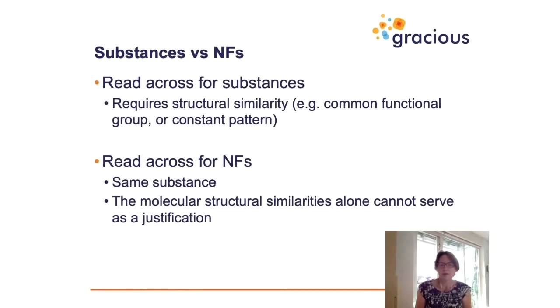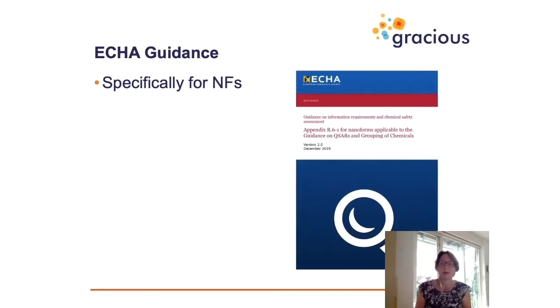So for nanoforms, read across is used in general only within the same substance, so only within titanium dioxide. But then the molecular similarities, the molecular structure, the TiO2, is not sufficient for read across. There needs to be more than just that it is also TiO2. And this is elaborated further in this ECHA guidance specifically for nanoforms.